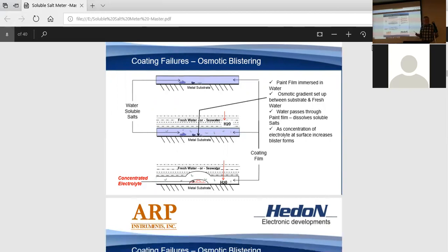But what happens in the field, especially in immersion, underwater hull tanks, ballast tanks, and they have ballast tanks in cruise ships, right? In seawater or freshwater, water molecules do breathe through the coating. That's a known fact, not a problem. It happens, even with the best of coatings. But when it does, and there is that contamination of soluble salts with this water, you create a concentrated electrolyte solution. And what happens then is you get what's called osmotic blistering, because it's trying to equalize equilibrium between the fresh water and the surface. And you actually break the bond of the coating and the blisters form. That's why you see blistering of coating systems. Osmotic blistering is what it's called.